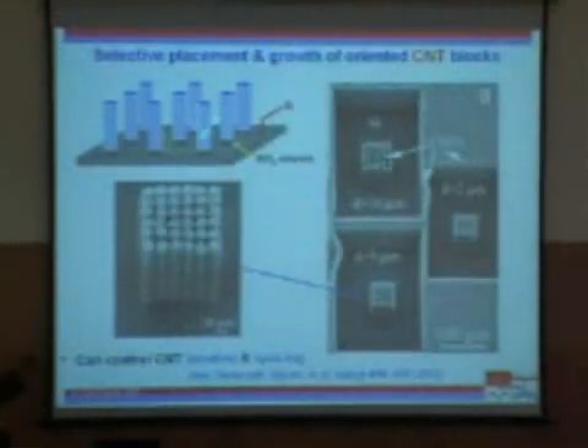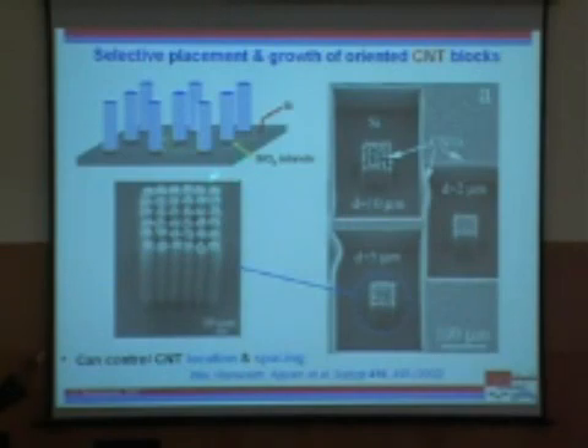The true power of this particular method of growth is that suppose I provide enough surface area on the side as well. Now I can actually get two-dimensional growth. And by extension I can get multidirectional growth by just chiseling the silica surfaces, because the carbon nanotubes inherit the topography of the silica. If you had noticed earlier, there was no growth laterally, and that's actually quite an important point which I'll touch upon later. So here I'm just providing a solution: I provide more surface area and I'll get growth like this.